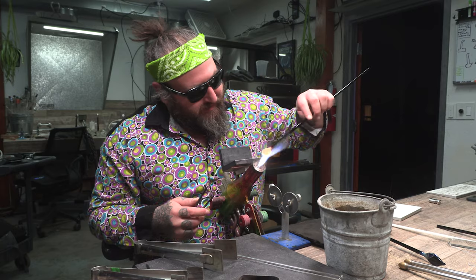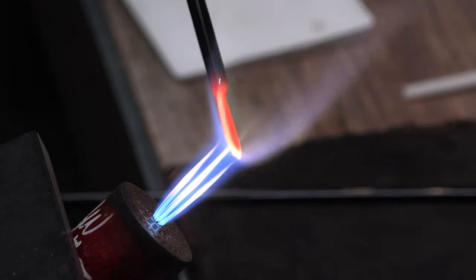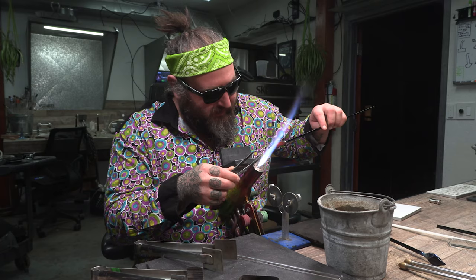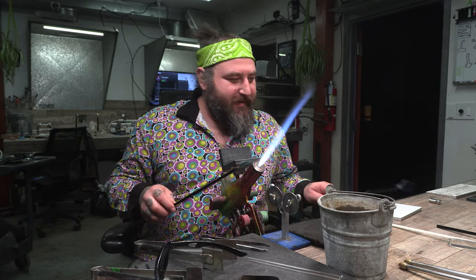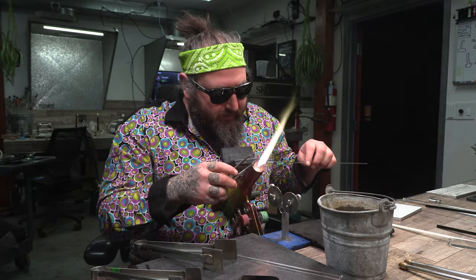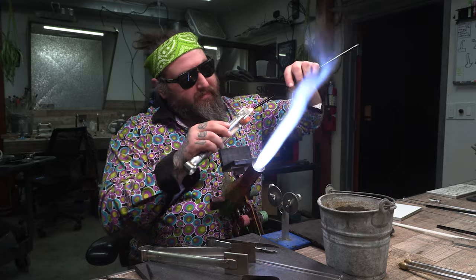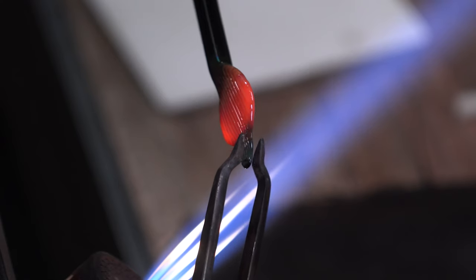Give it a mash with the masher — using one with lines in the paddle to give a little more texture. Heat it up with a nice even heat and stretch it out with your tweezers. As it stretches out, keep the heat tapered so it makes the shape of a leaf — the taper of a leaf. Pull as it starts to cool. You're comparing the red and the blue — you can see lines of red and blue in it. The blue is from the silver and the red is probably from the copper. Take it off the rod on a nice little 3mm punty — that'll be ready for connection. Make a whole bunch of these, six or ten — pick how many you think you'll need to go around it.